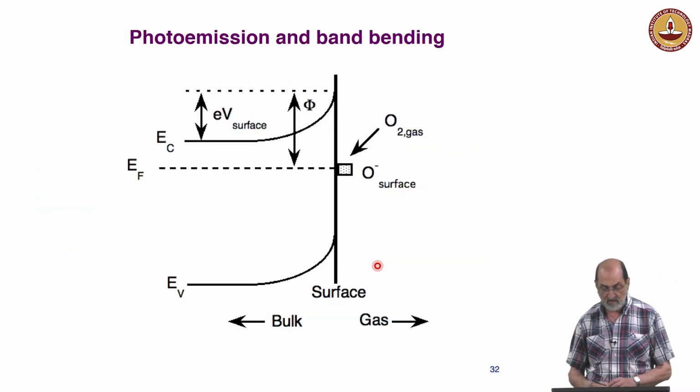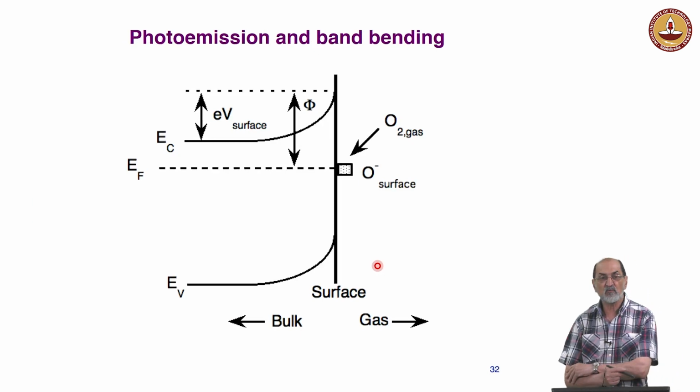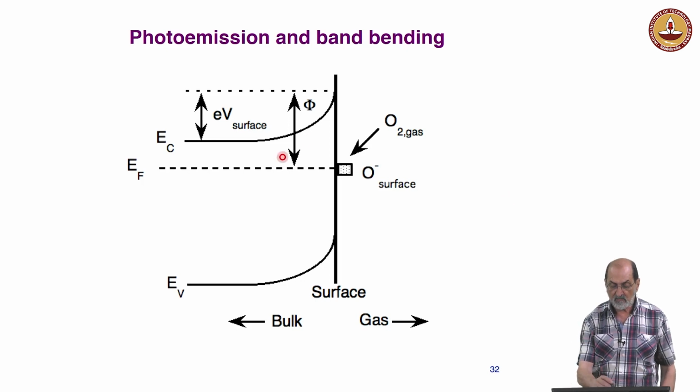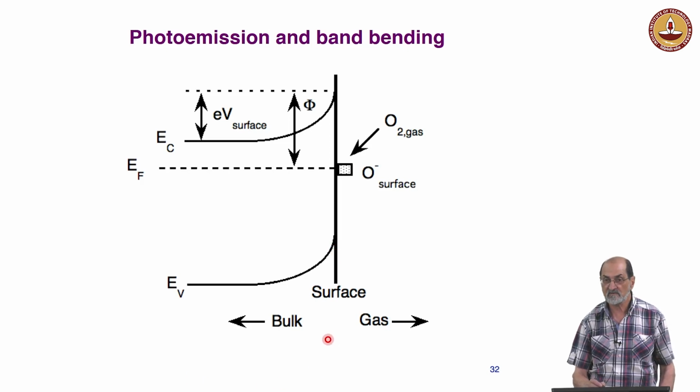Well, we have to remember how photoemission works. This is the general situation. When we have band bending, the internal levels also follow the band bending because it is an electrostatic potential. The whole thing goes up or down. So what happens at the surface, whether or not we have band bending, is going to be reflected in the binding energy when we run photoemission.